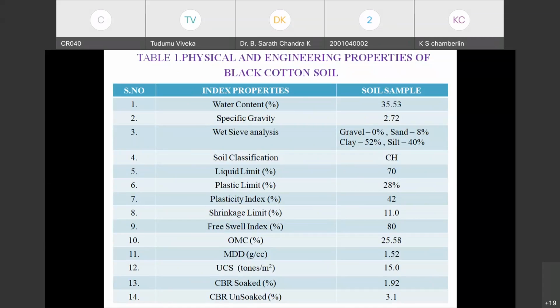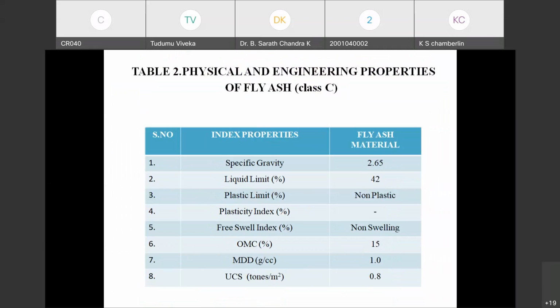Next one: liquid limit is 70%, plastic limit is 28%, plasticity index is 42%, shrinkage limit is 11.0, free swell index is 80, OMC is 25.58, MDD is 1.52 gram per cc, UCS is 15.0 tons per meter square, CBR soaked is 1.92%, CBR unsoaked is 3.1.